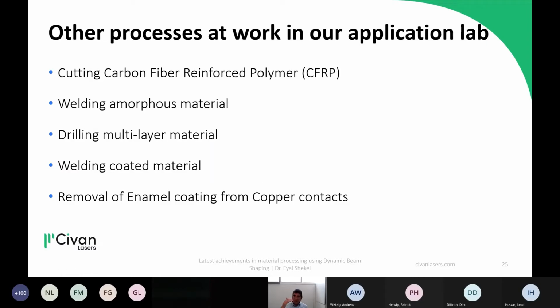So, without showing more details, just to say other things that are happening currently in our application lab: cutting of carbon fiber reinforced polymer, CFRP, welding of amorphous materials, drilling of multi-layer materials, welding coated materials, and removal of coating. This is actually, like Patrick mentioned, where our laser can start overlapping with pulsed lasers. Because we have such high power density and move so fast, it starts working like a pulsed laser. So some applications that today are done with a pulsed laser, we can do with our laser, and then you can use the same laser to do different processing, like here, for example, to remove the coating and then do the welding.